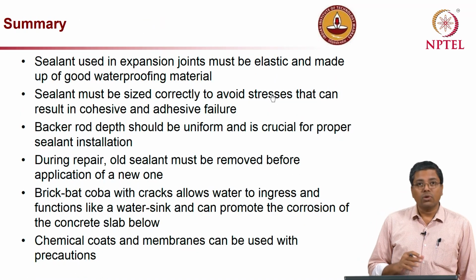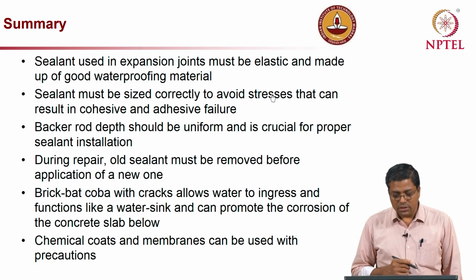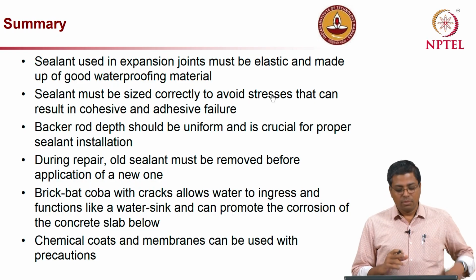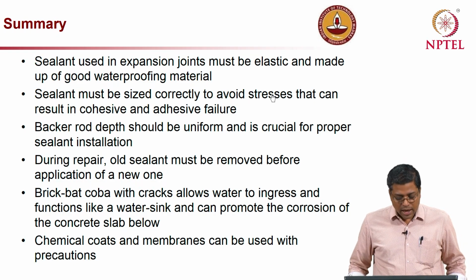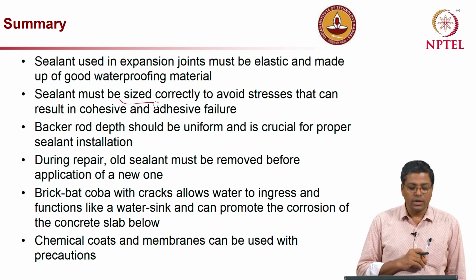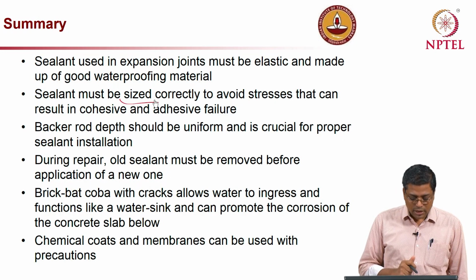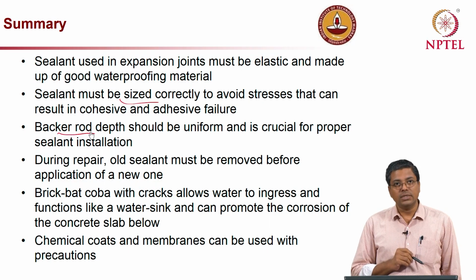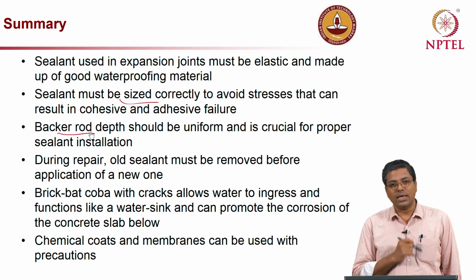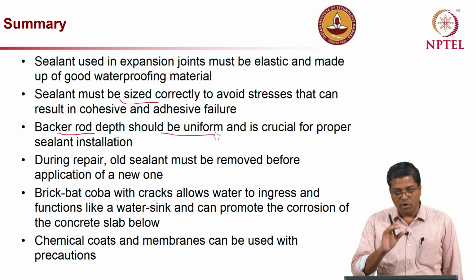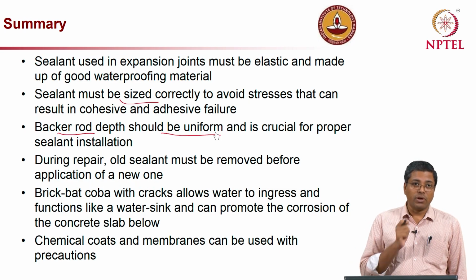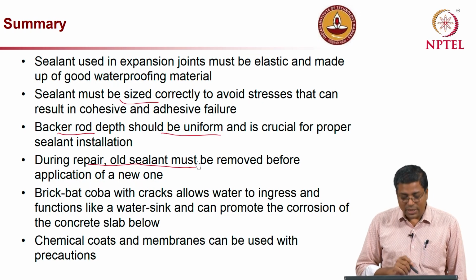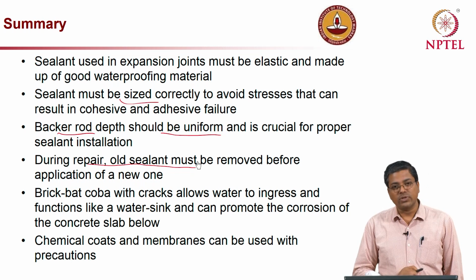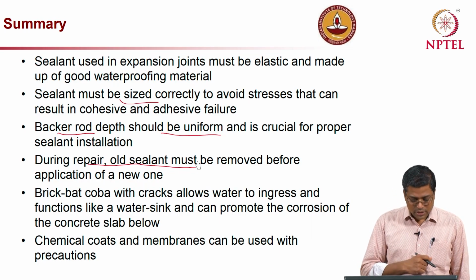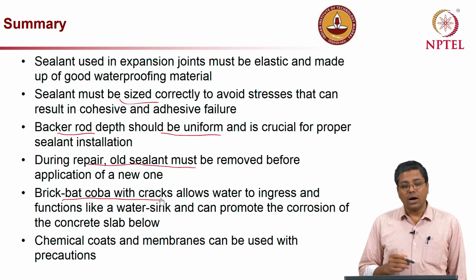With that we will summarize this. So, we talked about sealants used in expansion joints and what are the properties of that. They should be elastic, made of good, highly water impermeable material, and also the size of the sealant is very important, because the failure mechanism will depend on the thickness of the sealant, and the backer rod we discussed in detail how important they are in ensuring that the sealant actually performs very well. So, they should be inserted in a uniform manner, uniform depth, and that is very crucial for the performance of the sealant. Now, during repair also old sealant must be completely removed, and the inside concrete surface should be ground, so that the new sealant will bond very well with the concrete surface inside the joint.